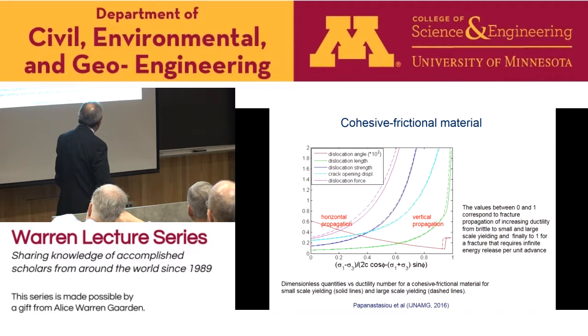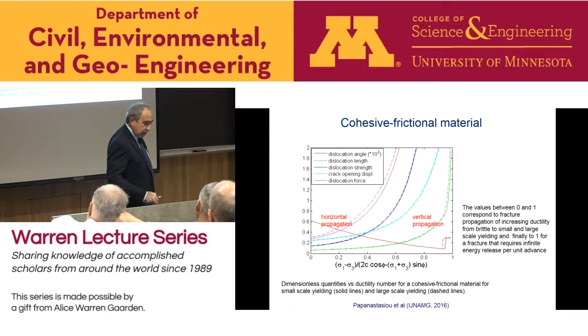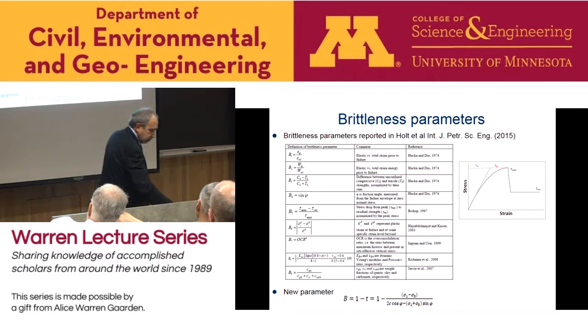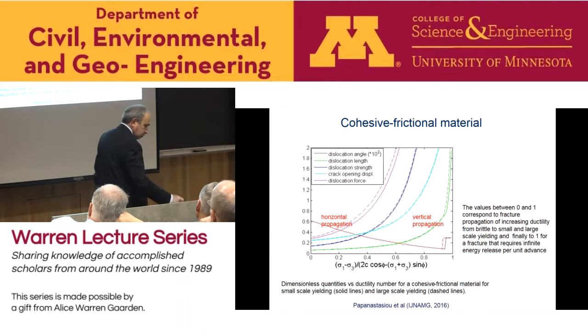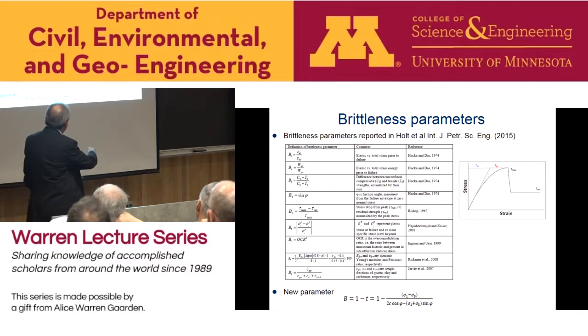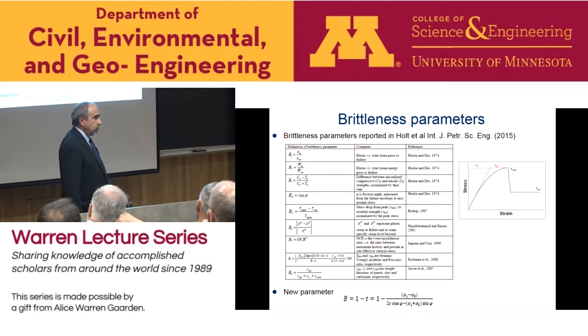And if we look at this diagram, we say that the values of 0 to 1 correspond to fracture propagation of increasing ductility from brittle to small scale to large scale, and to 1, which will correspond to the case that we require infinite energy release for unit advance. And again, I introduced this parameter here, which was basically this one. I just took 1 minus that parameter to be consistent with some other brittleness parameters which were proposed in the literature. We say that we need a brittleness index to use as a candidate selection for intervals to do hydraulic fracturing in shale reservoirs, okay?